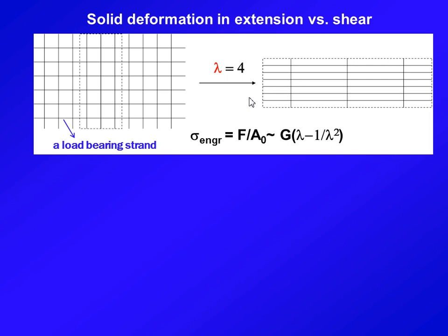Meanwhile, my area has dropped by a factor of 4 without question. So in that limit of no escaping of entanglement, you have something that we can resort to the class of rubber elasticity and perceive that my force will monotonically grow with extension.